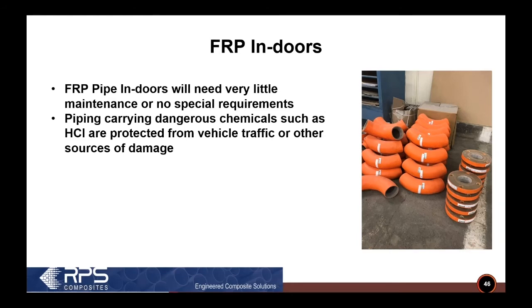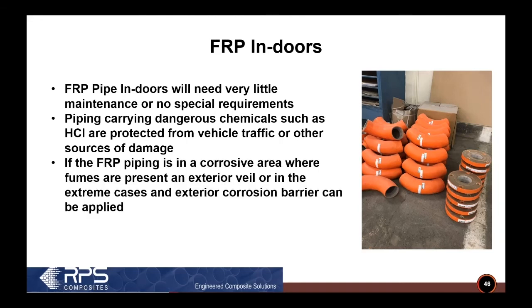When you use FRP piping indoors, not really any special requirements. Of course, if the pipe is carrying some dangerous chemicals, you'd need to protect it from vehicle traffic or other sources of damage. If it's in a corrosive area, one of the beauties of FRP piping is, the exterior corrosion resin that's on the pipe is pretty corrosion resistant compared to metallic pipe. It's not quite the same as the inside surface where you have a much thicker corrosion barrier, but that layer of resin and glass that's on the outside of the pipe is pretty corrosion resistant and gives you really good corrosion resistance in most environments.